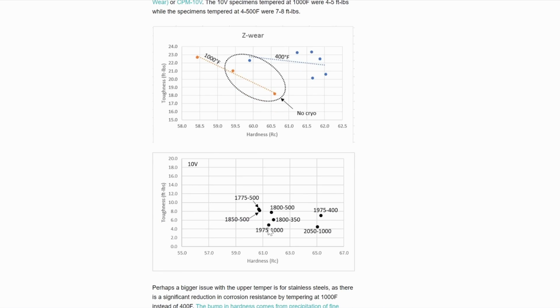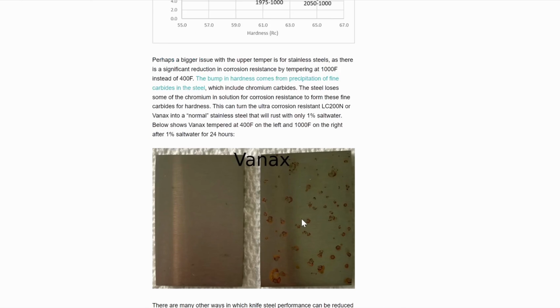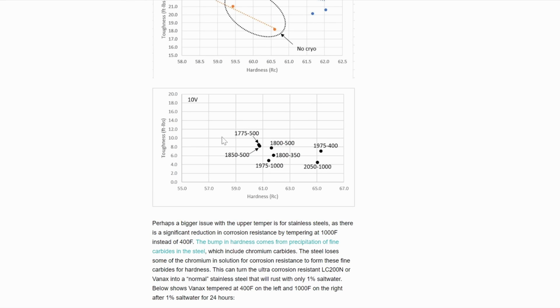Similar with 10V, these are the 1,000 degree tempers down here, where we got like between 4 and 5 foot-pounds. And when we tempered between 400 and 500 degrees, we got around 7 to 8 foot-pounds. So a significant improvement in toughness at the same hardness. So a reduction in corrosion resistance, a small reduction in toughness. I prefer tempering in the low temperature regime rather than the high temperature regime.